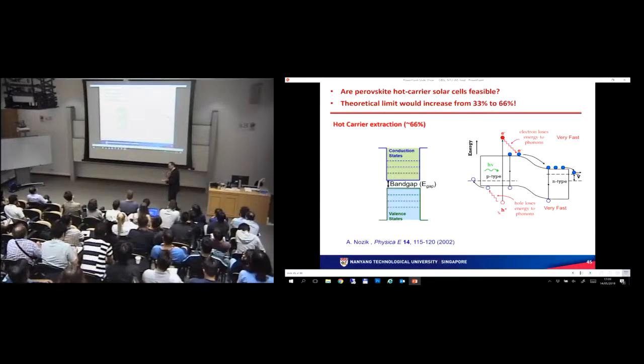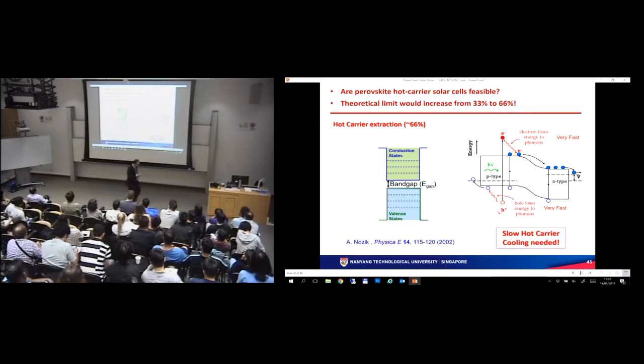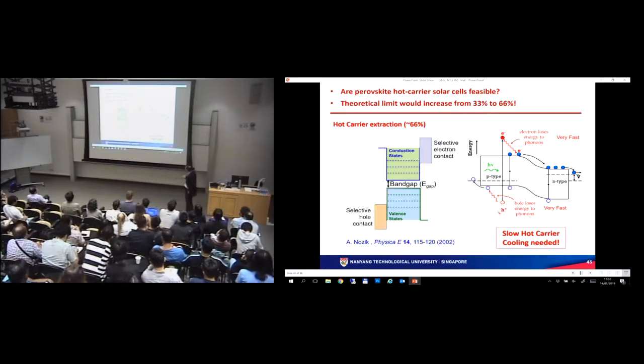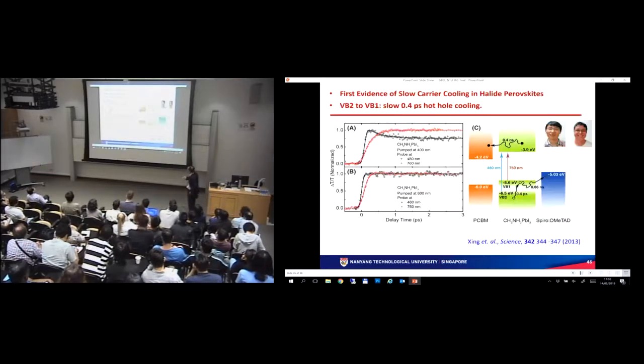Now it's a very enticing concept because you can increase the theoretical efficiency up to 66%. Our motivation is to look at whether the science is there for this concept to be even feasible in the first place. Just a reminder, in this case, you excite with selective electron contacts. You want to extract the hot electron and hot holes before they have a chance to relax to the band edge.